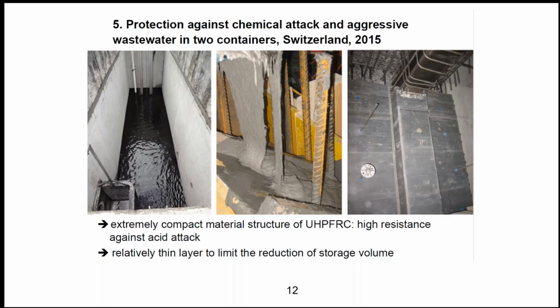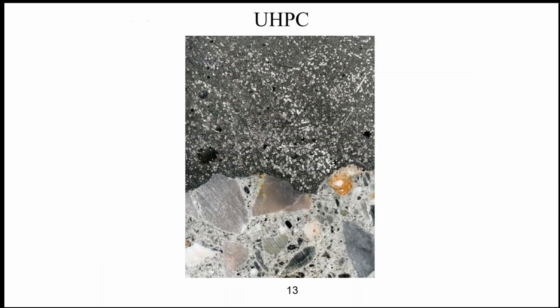The rapid chloride permeability number, the number of Coulombs for this material, is very low. It's less than 100 compared to 3,000 that you get for conventional concrete. So that's one of the reasons that this material is very durable. And durability of the material really is one of the main reasons why we use this. It's a wonderful material for retrofit.